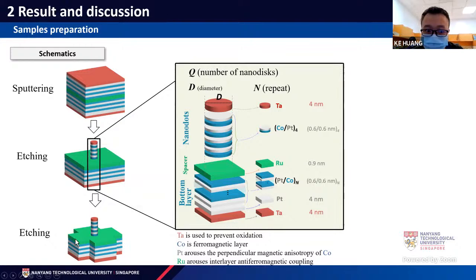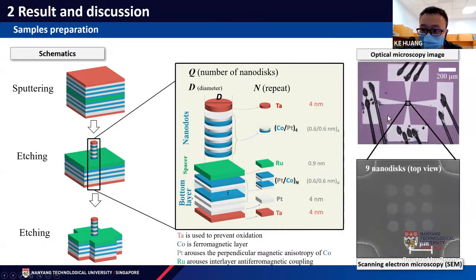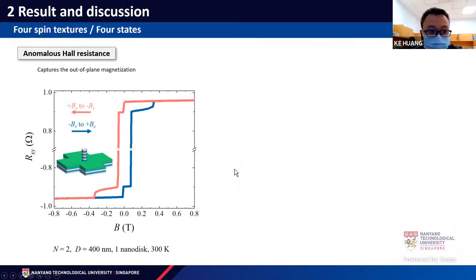Then we etch the bottom layer into a Hall bar cross because we want to measure the transport result. Here is a top view of the SEM and the optical image. In this work, we were changing the shape of this nanostructure: the diameter of the nanodisk, the repeats of the bottom Pt-cobalt layer, and the number of nanodisks. We were trying to see what's going on.